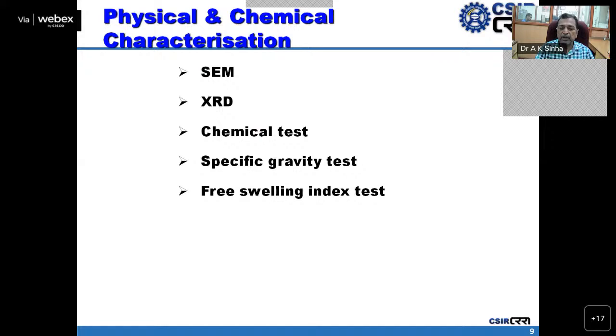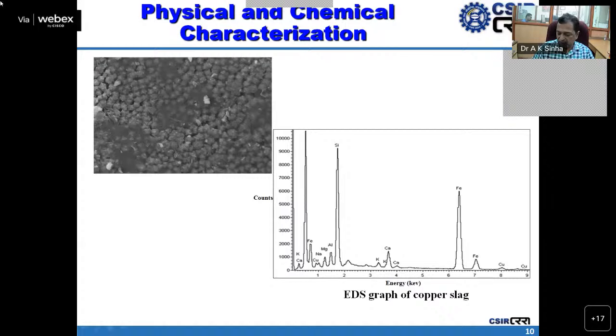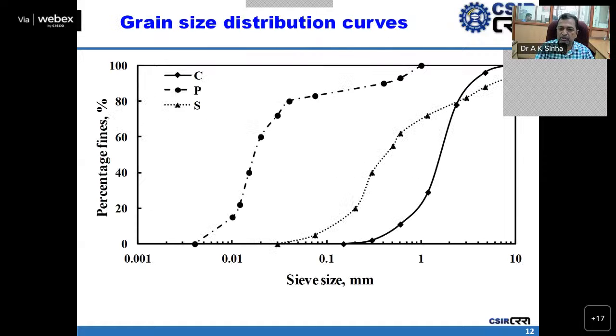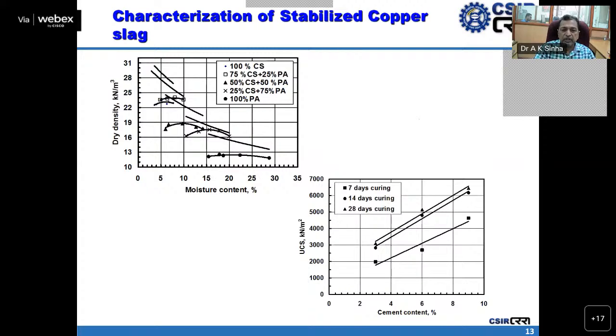In physical and chemical analysis, SEM, XRD, all those things were carried out, and these are the SEM photographs, and this is a coarse grained material. Similarly, geotechnical parameters were determined in the laboratory, and this is the grain size distribution curve of copper slag, pond ash and locally available material, and it is found that it is sand size particles and a poorly graded material. So it was blended with pond ash in different percentages from